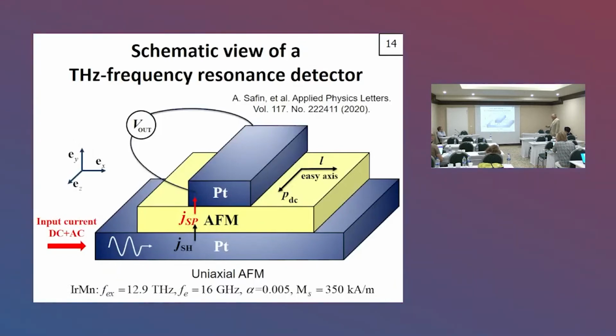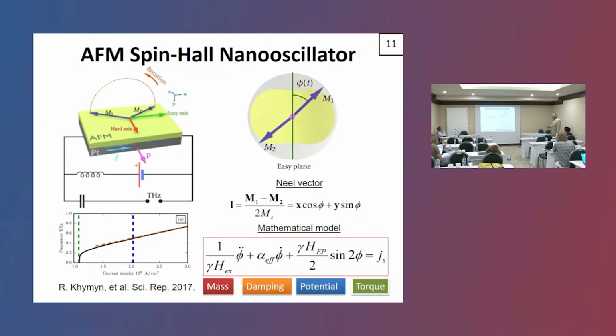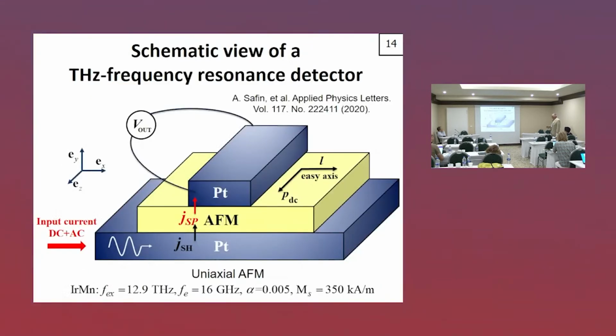Now the receiver. We will try to build the receiver using a very similar device. The device consists of the antiferromagnetic layer, a layer of platinum or any other heavy metal, where we will supply the AC signal, which is the signal which we are going to receive, plus a DC signal, which I will show can help us to change the resonance frequency in the antiferromagnetic material. And the top layer will actually receive the signal obtained due to the magnetization dynamics in the antiferromagnet using the inverse spin Hall effect.